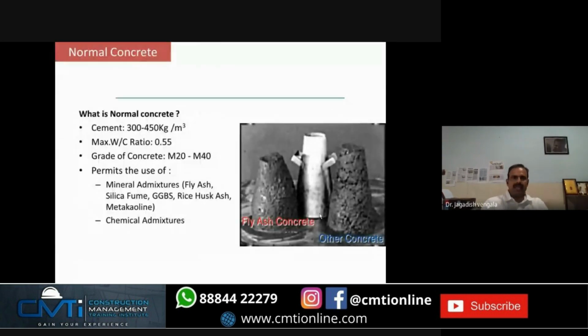And you can see here, when you sum up the previous slide, the cement you take for normal concrete is between 300 to 450 kgs. And a maximum of 0.55 water cement ratio you will take up, to maintain the workability and at the same time minimize the voids so that you get reasonably dense concrete. And grade of concrete between M20 and M40.